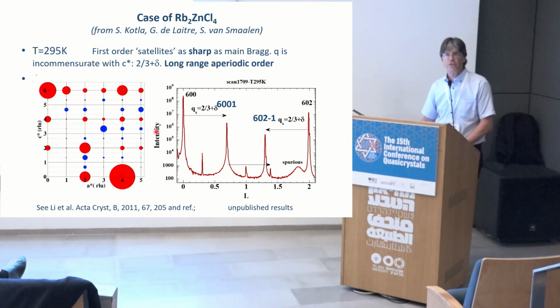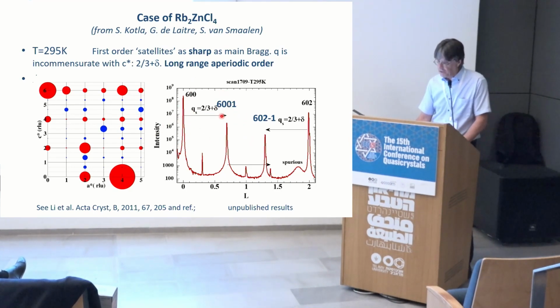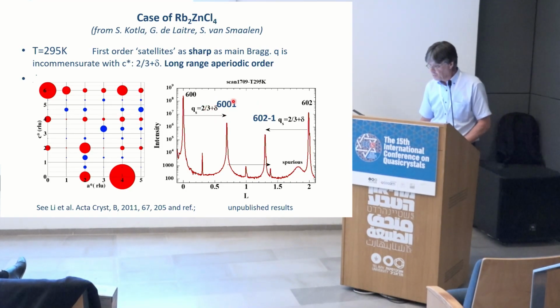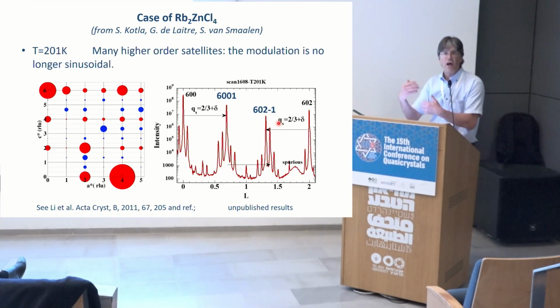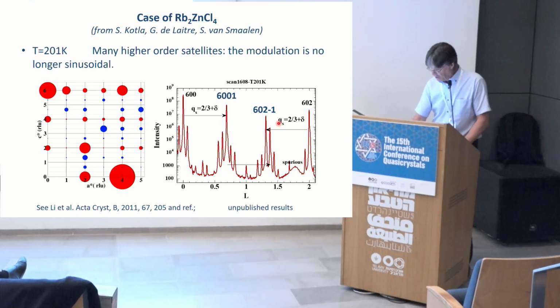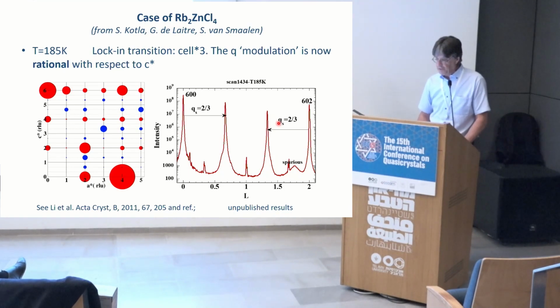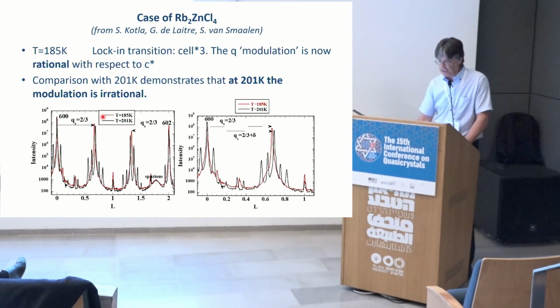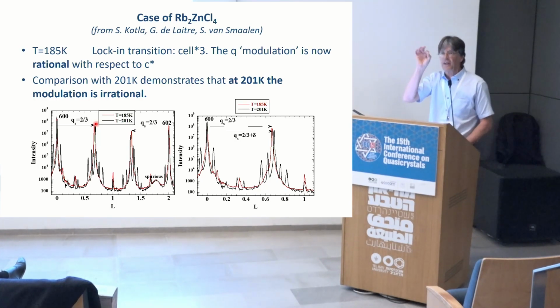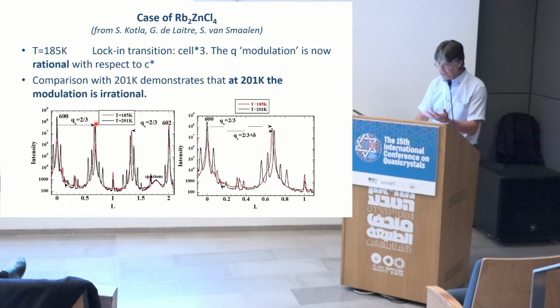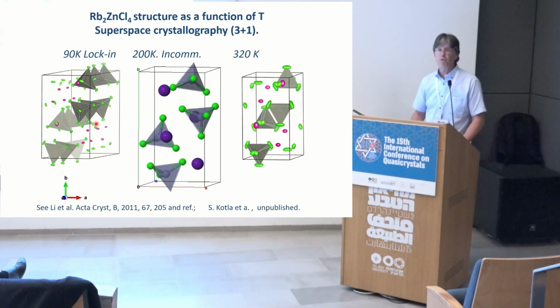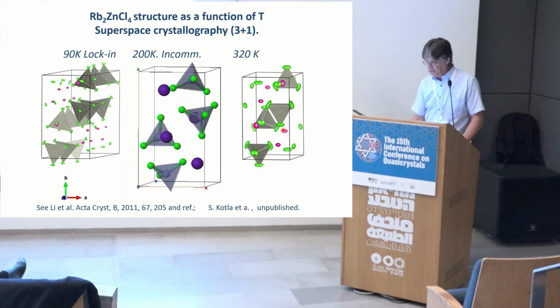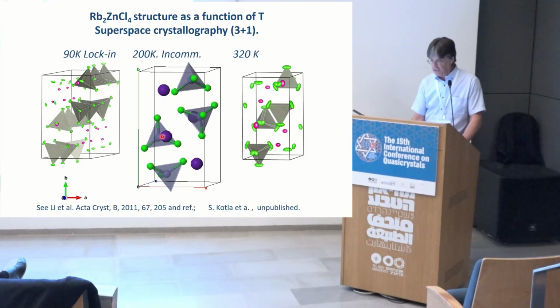And from that, you can derive the wavelengths of the satellites and index your diffraction pattern, not with three indices, but four indices. So this is 1 and minus 1 here. If you cool down, you have even more harmonics, higher orders of the satellites showing up, which makes the diffraction pattern even more complicated. And if you go down even further, everything collapses and goes to a rational approximant. So the comparison between these two temperatures is a clear indication that before this two-thirds plus delta, delta is really an incommensurate structure. And using this high-dimensional approach, one can derive the structure. I show you here the three different states: the high-temperature disordered state, the low-temperature three-times periodicity, and in between we have this incommensurate phase.